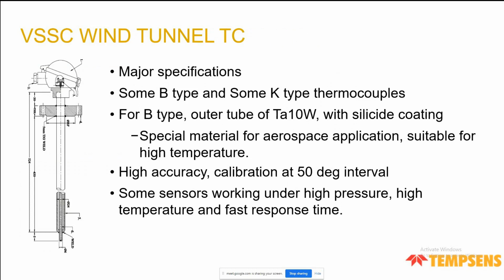So we supplied to Vikram Sarabhai Space Research Center the wind tunnel thermocouples. Earlier these were being imported, and we supplied B-type thermocouples and K-type thermocouples. The outer tube was tantalum tungsten 10% with silicide coating. This is a special material which is used for aerospace application. This wind tunnel is one of the highest speed wind tunnels in the world, and we have supplied them these thermocouples, which have to be fast response because the experiment is a very short time experiment.